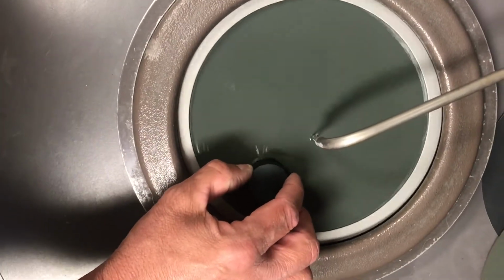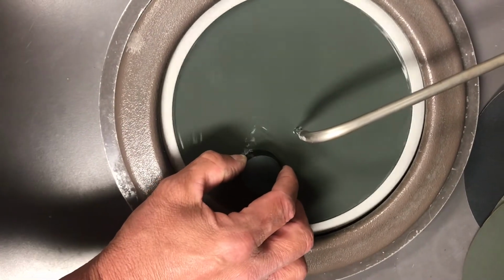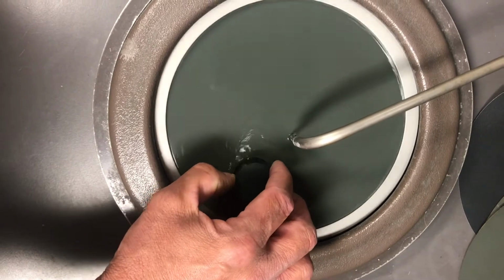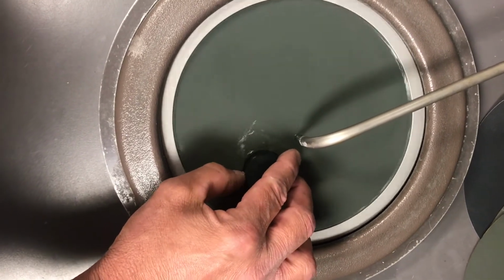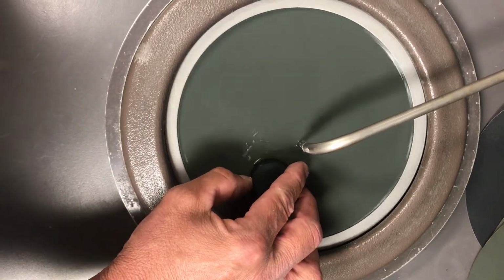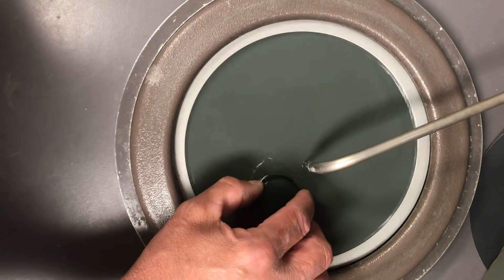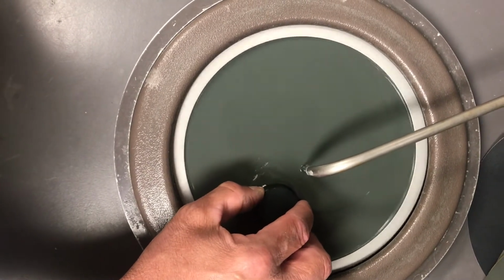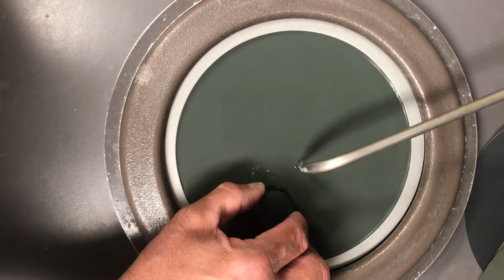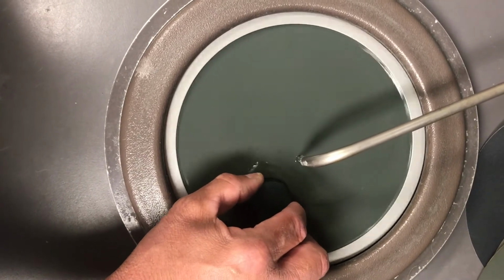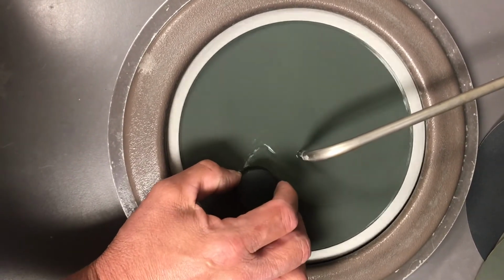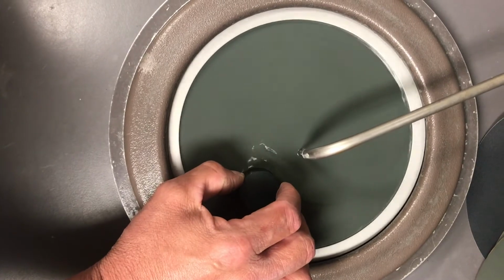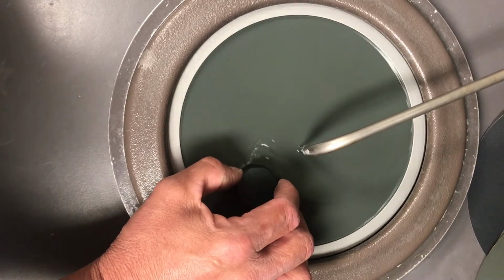There is a whole lot less risk of injury in this process, but you can still polish the tips of your fingers, and that is painful. Just avoid that. Gentle pressure. I like to rotate my sample a little bit while I polish, but the last few seconds, keep it in one orientation. Again, so you can see the scratches are in one direction.